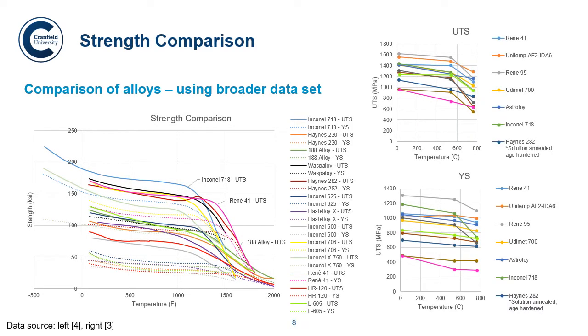So first we looked at our strength comparison of all the alloys, which used the broader data set. On the left you can see the MMPDS document, and on the right is the data from the Superalloys technical guide book, which actually does have more alloys than the MMPDS document. But the information that the MMPDS does have on the alloys that are included is quite detailed. You can see the solid lines are representing UTS for the alloys, and the dotted lines are the yield strength of the alloys at obviously different temperature ranges.